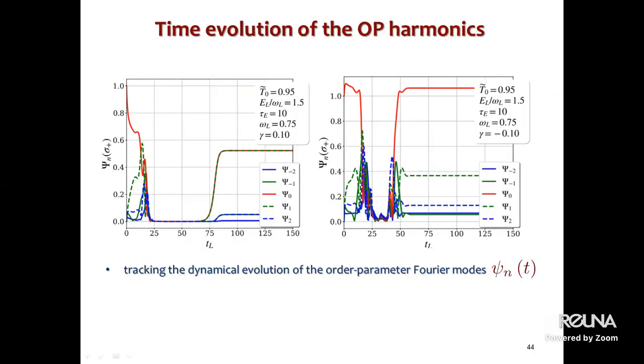Here we track, again, the modes of the order parameter. So we track here the dynamical evolution of the order parameter as a function of time for a single noise realization, for gamma equal here minus 0.1 and here plus 0.1. In the case of a negative, cold defect, the critical temperature is smaller than the branching point and the mixed state is not realized, and the system relaxes into a current-carrying state dominated by a single harmonic. In this particular case, the dominant harmonic, shown in red, is 0. So there is a current. Because they are not equal, the current will flow in the counterclockwise direction.